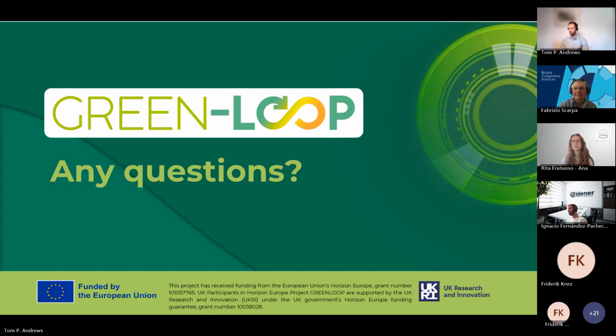Thank you, Tom. A nice presentation from all the speakers. My question is for Zach's presentation regarding the use of lignin. The results with respect to the flame retardant, and more specifically the use of lignin. I'm not sure if you used crude lignin or native lignin, or a fraction of lignin. In case not, could you consider whether it is possible to enhance the behavior of a flame retardant if you use a fraction of lignin in a low molecular weight range, in order to improve the flame retardant capacity? Also, it is necessary to remove the sulfur content in order to reduce the toxic gases, referring to the oxides of sulfur, for example.